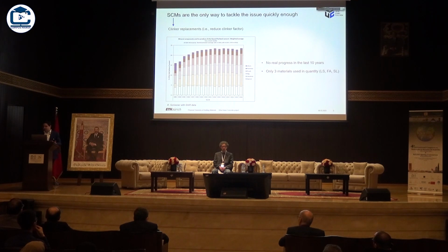And there are only 3 materials, limestone, fly ash, and slag, that we are using in quantity. And the reasons for this, you can think that they are diverse, but are mainly related to availability, as we will see in the next slide. The problem is that we are stuck in this range of 20 to 25% replacement, and on the other hand, we have roadmaps for CO2 savings, like the one that GCCA is proposing, which is aiming to get an average clinker factor by 2050 of 0.52. So the question is how we are going to materialize that average clinker factor of 0.52 in a situation where we got stuck already at 25% replacement. So we have halfway to go.